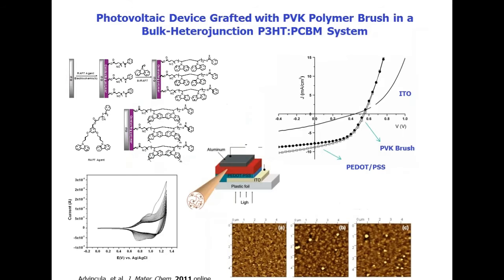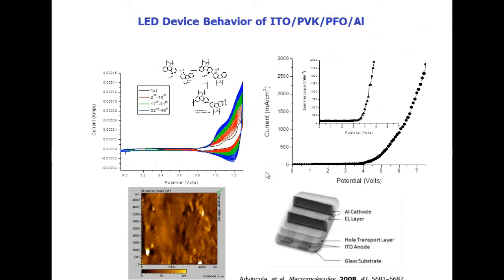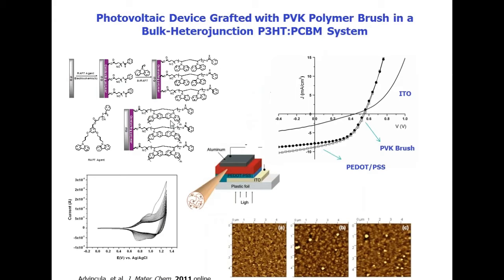On the other hand, the same scheme can be done with a solar cell based on a bulk heterojunction system, such as polythiophene and PCBM, a fullerene material, where we grafted the polymer through a polymer brush and then utilized cross-linking in order to produce a cross-linked film. And here are the different stages by which we started with an ITO, a polymer grafted brush, and then a polymer electro cross-linked PVK, showing the change in the morphology.